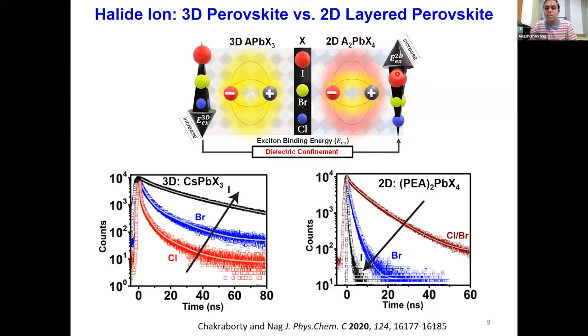And this difference in the excitonic binding energy trend also gives a difference in optical properties. So for example, you'll see that in a 3D perovskite, the excitonic binding energy decreases from chloride to iodide, and therefore the photoluminescence lifetime increases as you go from chloride to iodide, and it reverses the trend when you go to 2D layered perovskite.